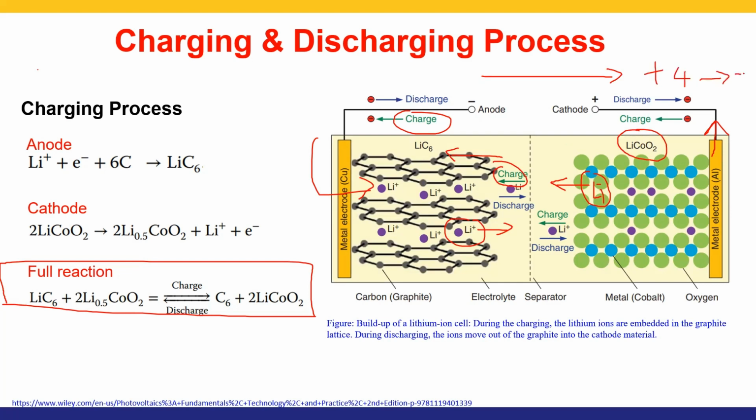Now, one interesting remark to make is that the cobalt electrode reaction is only reversible for x less than 0.5, and x is in mole units. So it limits the depth of discharge. Otherwise, the lithium cobalt oxide will be destabilized. The structure will crash or collapse very easily. So to maintain the structure's integrity or stability, the depth of discharge cannot be more than 0.5 moles of lithium.